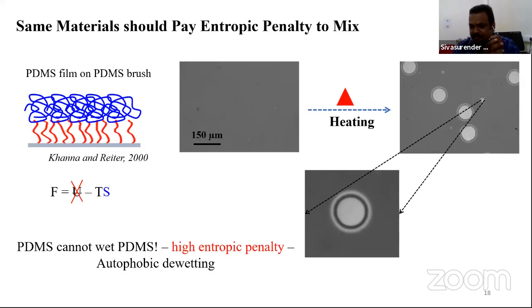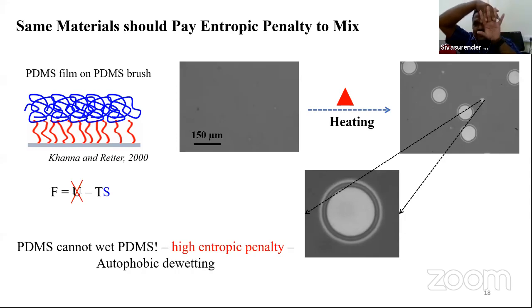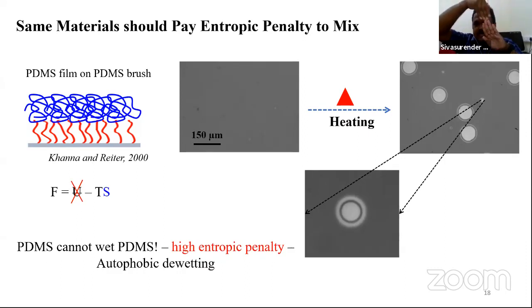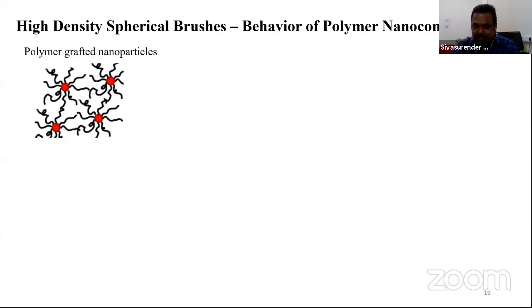So PDMS cannot form a very stable layer on top of PDMS because of the high entropic penalty. If these coils want to interpenetrate, they have to provide some space so that these chains can go and interpenetrate. Because of the high density, they cannot do that, and the entropic penalty is too high, right? And thus, by manipulating entropy, we could make materials of the same nature dislike each other. And it's not just here. We could also do it with curved surfaces, with polymer, with nanoparticles.